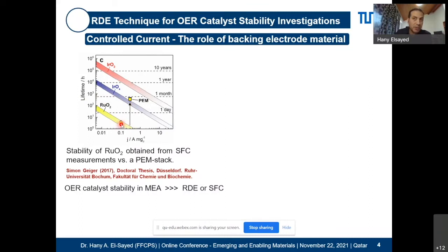So what I'm trying to say is, whatever catalyst you test in MEA configuration will last at least 2 orders of magnitude longer compared to the catalyst that you study using the RDE. And that's the conclusion here. The OER catalyst stability in MEA is much larger compared to the RDE.